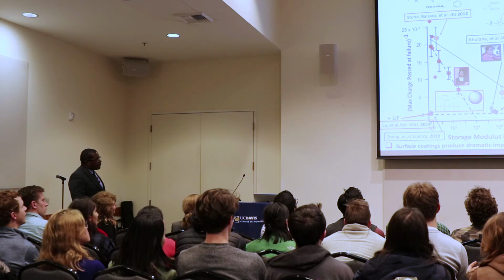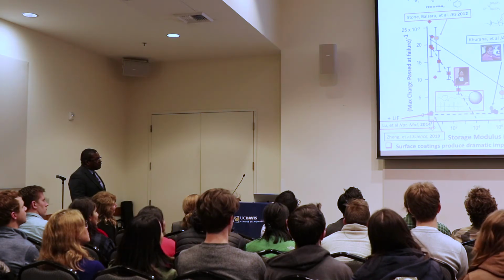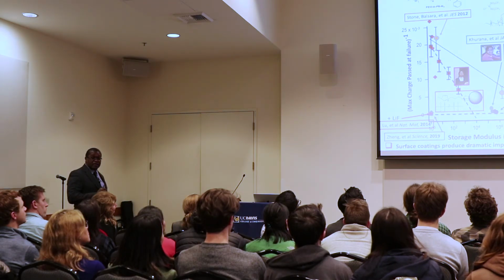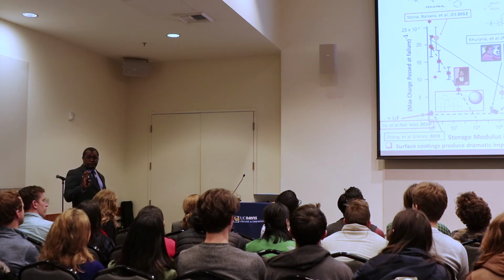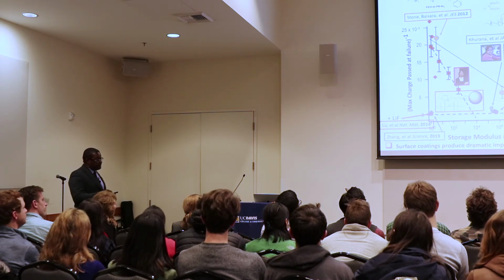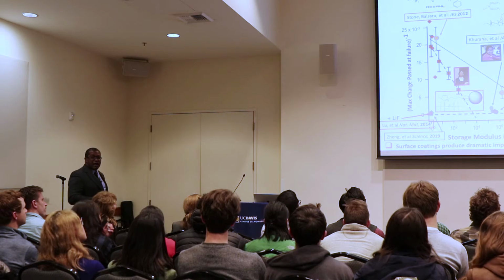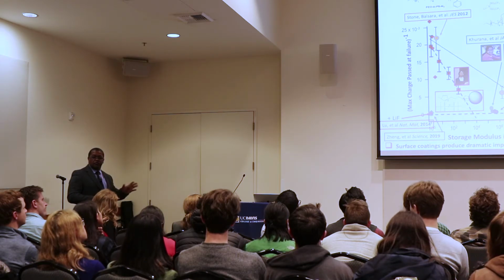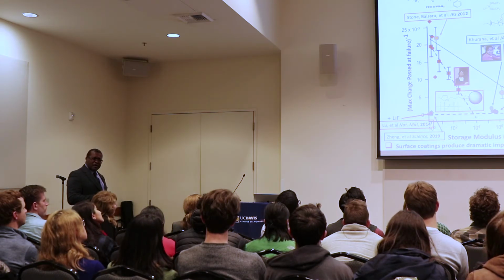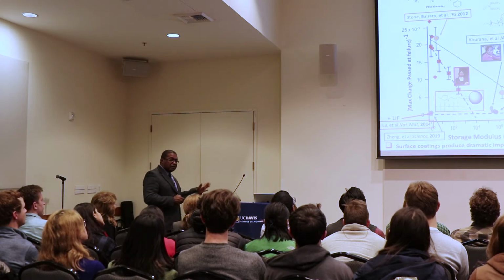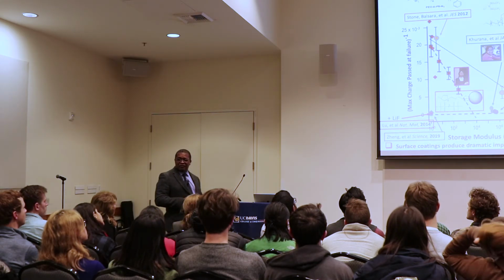So the really big surprise is this point here. This is a liquid electrolyte, no nanopores, just a simple electrolyte, we added the lithium fluoride, and it's stable like you wouldn't expect. That was unexpected. It obviously is in complete disagreement with the model.